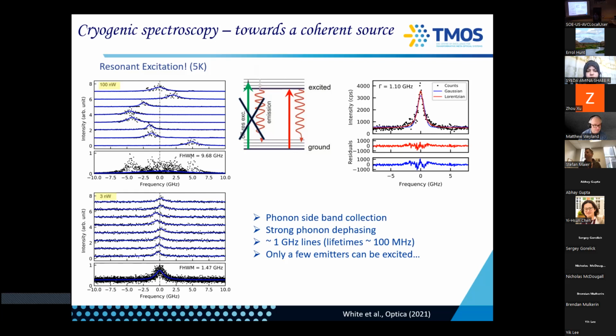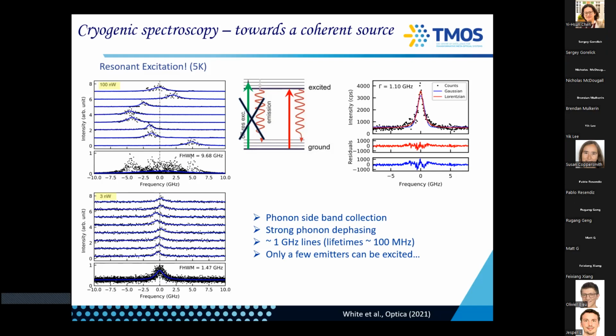And you can also see that this type of lines, you only get at low excitation power. So this is nanowatts. If you increase the excitation power, you will observe the spectral jumps, also called spectral diffusion. And that means that the system really is going to the excited states, and then there is a random Stark shift. You spectrally diffuse, then you excite again, you spectrally diffuse. And that's very not ideal because after the first scan, you basically have no emitter. So you scan with your laser, you excite it, you get a photon, and then it's being kicked out to a different frequency. So this is something that you want to avoid.